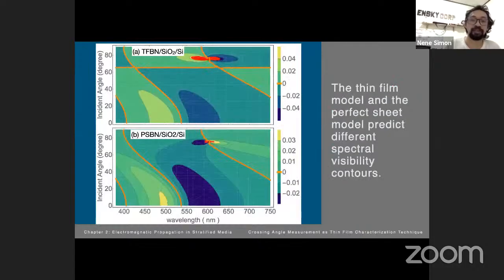So to further reinforce this, we plot the spectral contrast with respect to the incident angle as shown in this plot. They predict different contours, with the thin film model predicting total invisibility of boron nitride at an incident angle equal to the Brewster angle of the boron nitride. We can see it from this line. So at this particular angle here, whatever wavelength you use in the visible region, boron nitride is invisible.